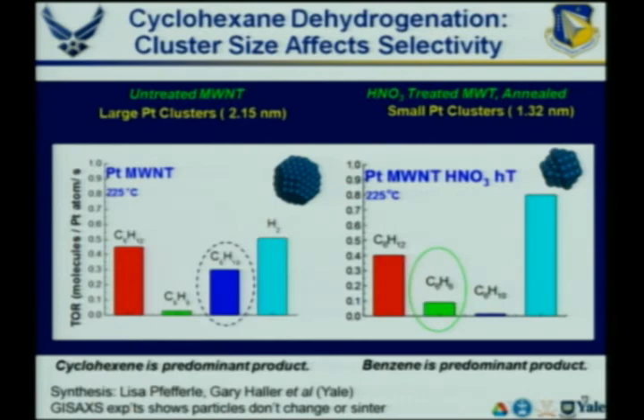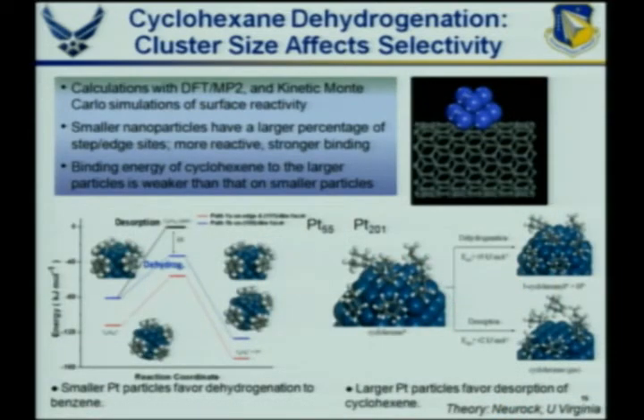But as you use the smaller platinum nanostructures, and smaller, not that much smaller, going from 2.15 nanometers to 1.32 nanometers, you get different reactivity. This product goes away, then benzene becomes the major product. You have more dehydrogenation. So as part of this team, Matt Neurock, who's a theoretical chemist and chemical engineer at University of Virginia, tried to understand what was going on there, and tried to model this. In order to do this, you have to use a number of different types of calculations, electronic structure calculations to get structures and energetics, as well as kinetic Monte Carlo simulations to understand the kinetic processes going on.